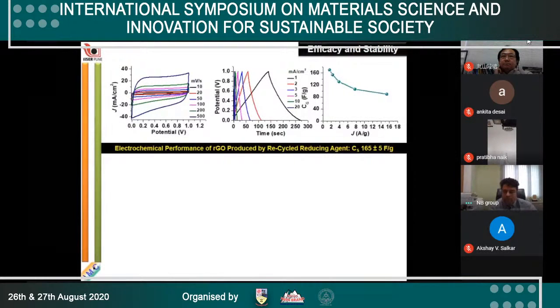As I was mentioning, this is the supercapacitor performance of RGO produced by recycled reducing agent. And if we compare the first batch and the second batch, the capacitance values are within plus minus 5 farad per gram.